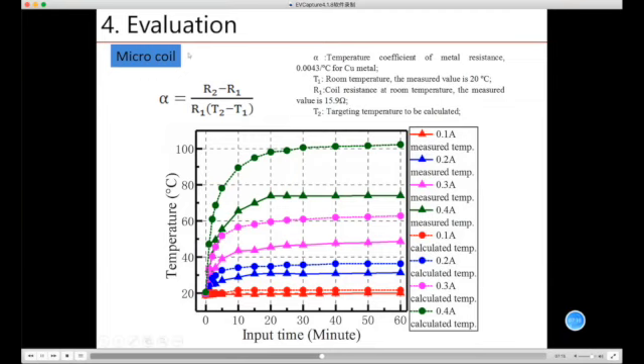In order to evaluate the microcoil performance, we input the DC current into the microcoil for a long time. And we change the current amplitude from 0.1 ampere to 0.4 ampere. And this figure shows the result of the calculated temperature and measured temperature. To calculate the temperature, we use this equation, in which R1 is the resistance at room temperature T1, and R2 is the resistance at the calculated temperature T2. And alpha is the temperature coefficient.